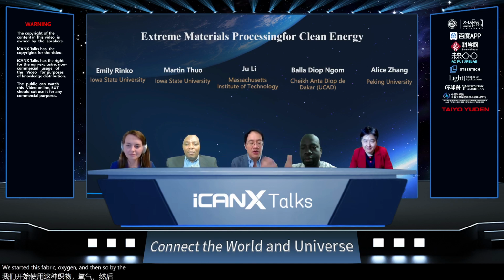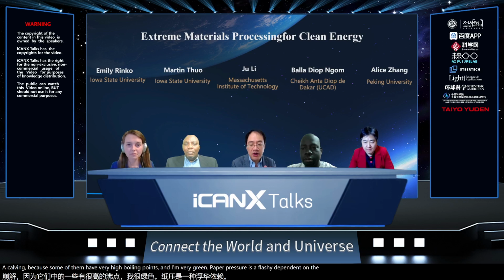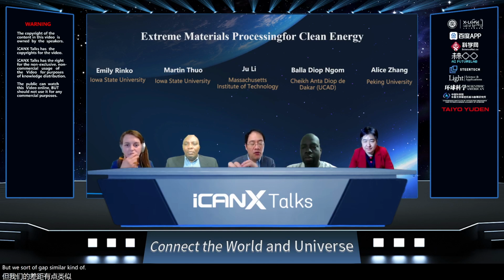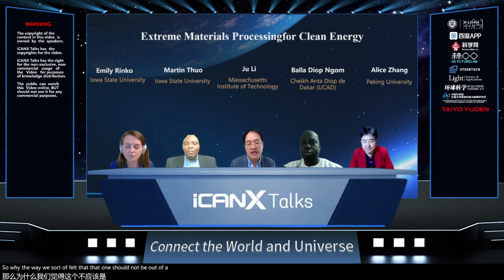Then, by the time I met Professor Liangbin Hu, we were discussing this, because he found this effect in the carbothermal shock. What we realized was that this cannot be a vapor process, because those metals have very different equilibrium vapor pressures, even up to 2000 Kelvin, because some of them have very high boiling points, and equilibrium vapor pressure is exponentially dependent on the boiling point. But we get similar proportions to the salt precursors we put on. So right away, we felt it should not be a vapor process, it should be a liquid-based